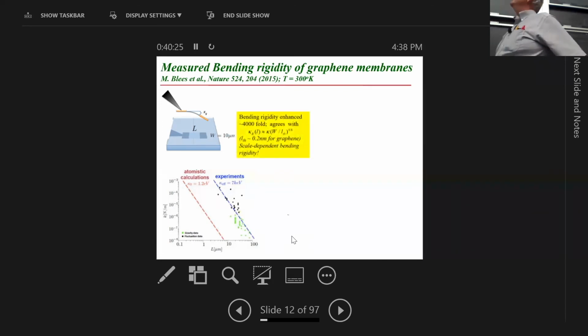And if you put the numbers into this formula, which is what the theory would predict, it does come out to be about 4,000. And if you don't like a 4,000-fold enhancement, you want something bigger, take your width not to be 10 microns, take it to be 50 microns, and it'll be 10,000-fold. So it depends on the size of the system, which takes some getting used to if you're a conventionally trained mechanical engineer or a physicist. It takes a long time to get used to it.